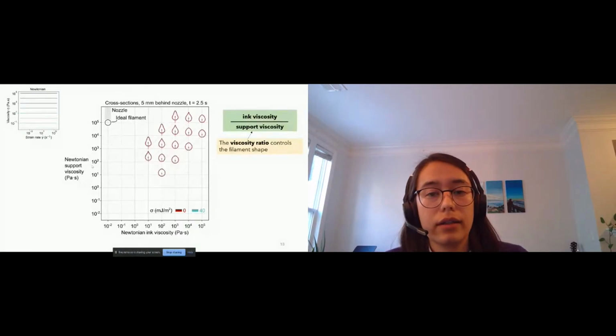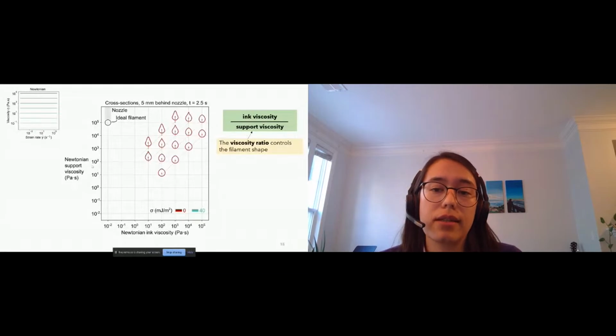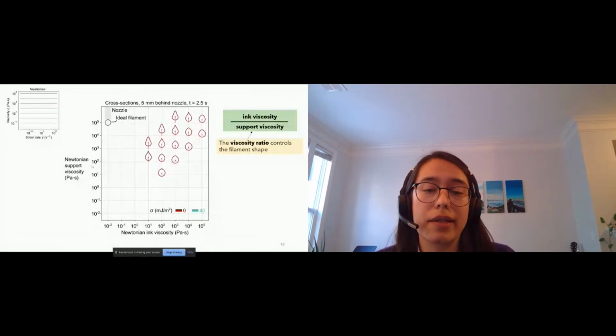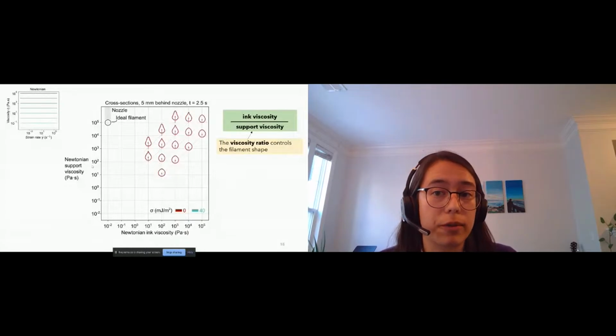And so here, what you can see is if you look down these diagonals, you can see that the cross-sectional shape is the same. So what that tells us is that the viscosity ratio is what's really controlling the filament shape here. So that's the ink viscosity divided by the support viscosity.